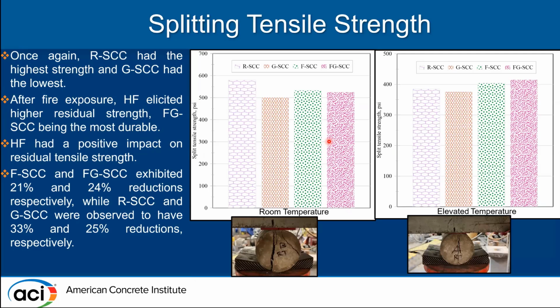Moving on to the splitting tensile strength, at room temperature, a similar pattern was observed where R-SCC reported higher splitting tensile strength, and G-SCC being the lowest, and the ones with the hybrid fibers being intermediate. However, after fire exposure, as you can see in the graph, the maximum was reported for the mixes containing the hybrid fibers, and the highest being the FG-SCC variant.